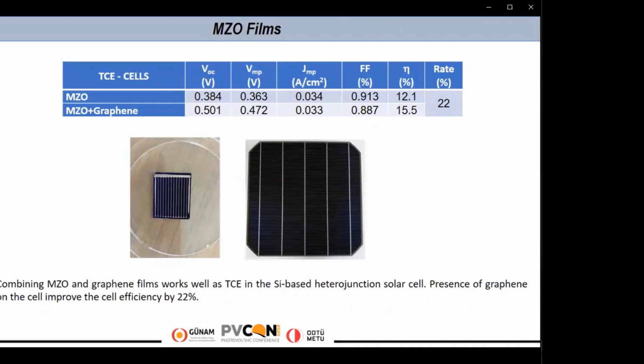On the other hand, VOC increased with the MZO graphene hybrid structure because graphene has a higher work function than MZO. MZO work function is approximately 4.1 electron volts, and the graphene work function is 4.5 electron volts. So we increased our solar cell efficiency with the graphene and MZO hybrid structure. It means that MZO and graphene can be used as transparent conductive electrode for the solar cell, especially silicon-based solar cell structure.